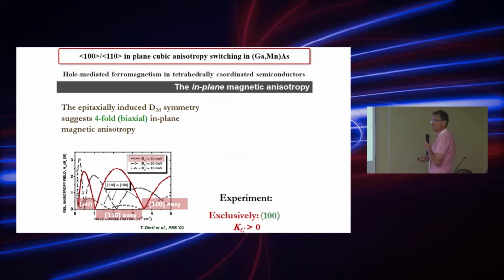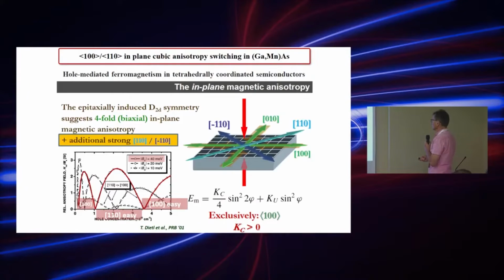However, the experiments, and there are many experiments done, indicated that exclusively the [100] orientation, the easy orientation for this cubic or biaxial term, has been observed. So in the language that is normally used to describe the magnetostatics of this material, the result is that the so-called cubic term, this fourfold in-plane symmetry, is positive, as I said, exclusively.